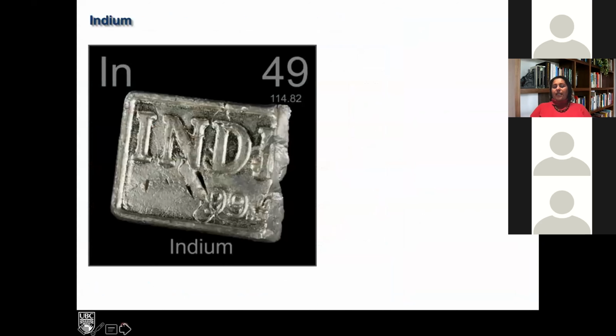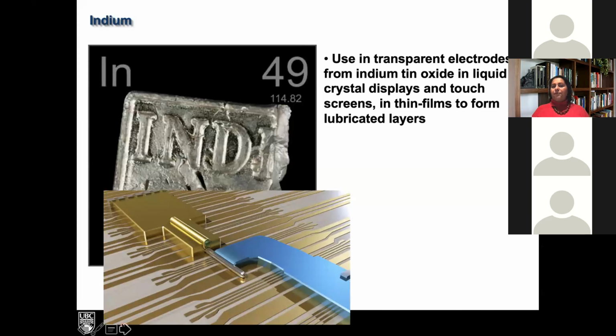So if I'm interested in developing functionalized polymers, high value polymers with functional groups, we chose from the very beginning to use indium. It's kind of a random metal to think about in the beginning, but where indium is used quite significantly in industry is, of course, in the indium tin oxides and the use in displays, etc. And if you have heard about indium scarcity, this is a question that a lot of people ask. Is indium scarce? Well, if indium tin oxide is going to be used in every single display on Earth, this will become a problem. So as a bulk material, as an element used in the bulk material, it actually can become scarce. Indium is generated as a byproduct of zinc mining.